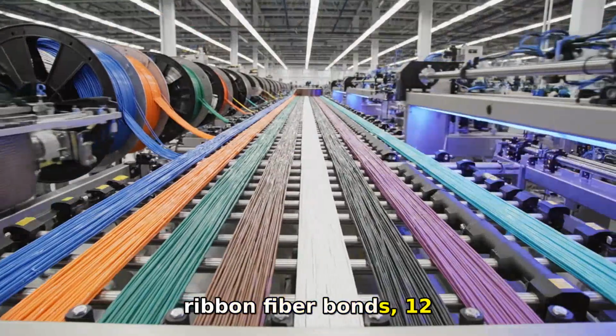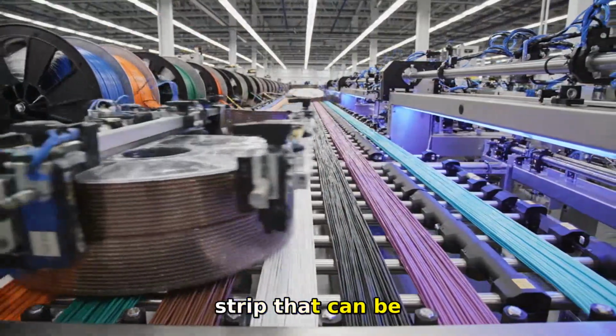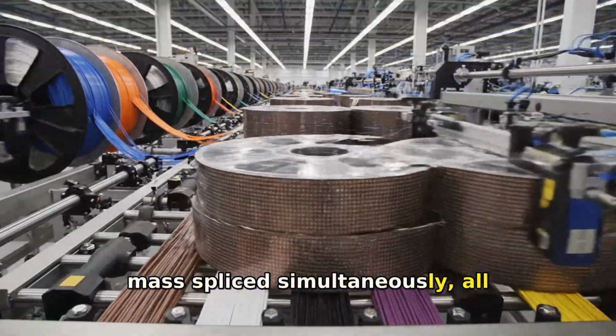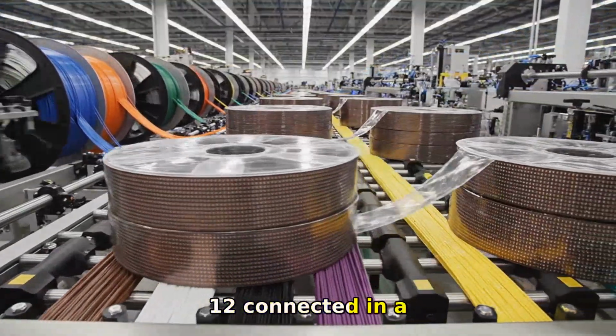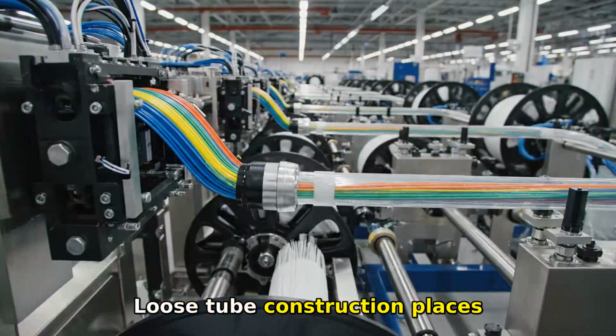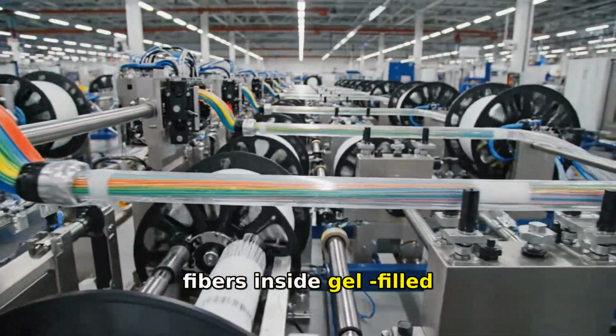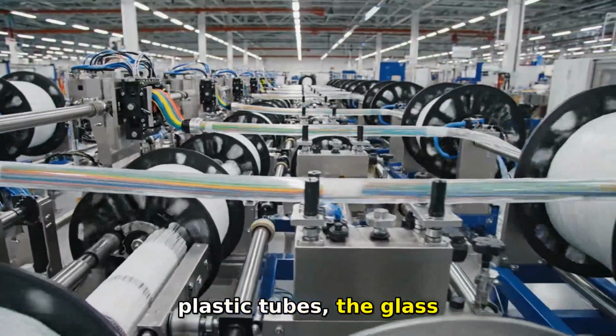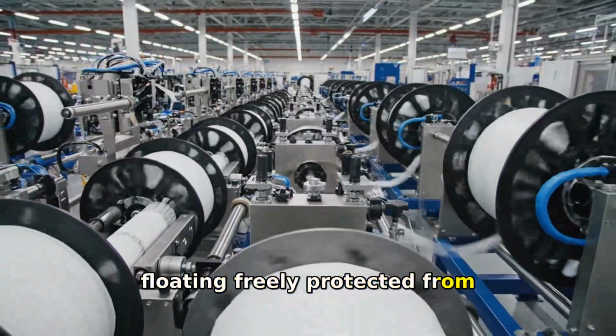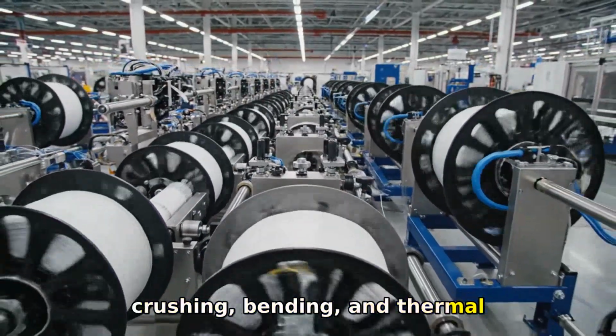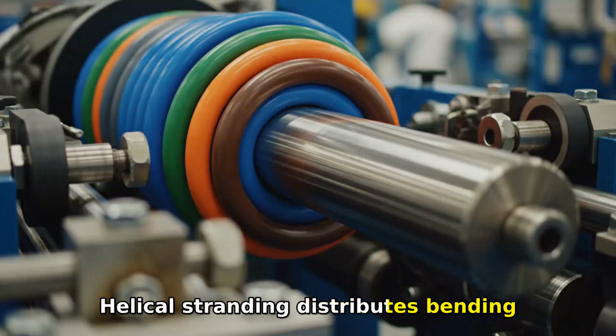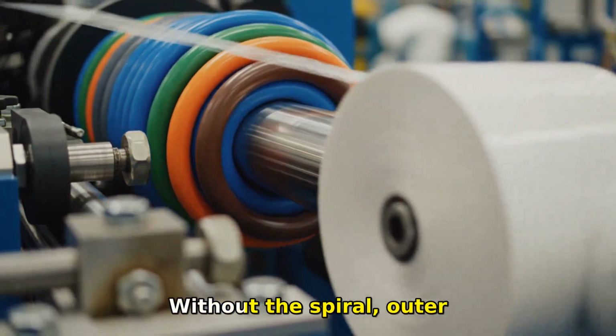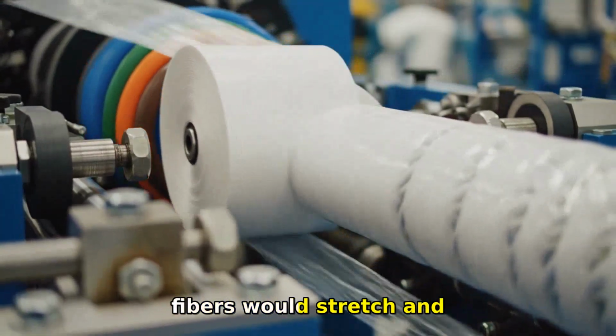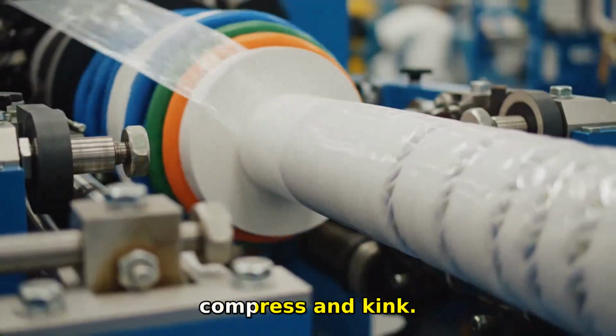Ribbon fiber bonds 12 fibers into a flat strip that can be mass spliced simultaneously. All 12 connected in a single operation. Loose tube construction places fibers inside gel-filled plastic tubes, the glass floating freely, protected from crushing, bending, and thermal forces. Helical stranding distributes bending stress evenly. Without the spiral, outer fibers would stretch and break while inner fibers compress and kink.